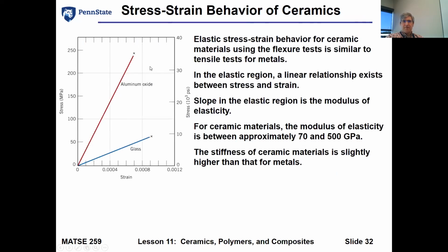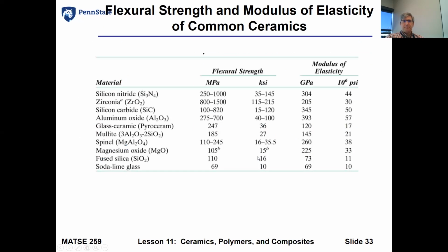It's going to fail. It fails in the elastic region. There's very low strains. You look at those numbers, it's far less than 0.1%. But you start looking at some of the flexural strengths, they start to get pretty good compared to what you might think, especially in silicon nitride. Zirconia is one that's widely used. Alumina is one of those other ceramics that is a widely used ceramic for a number of different things, but they are very stiff though in most cases, if you start really looking at the modulus of elasticity.